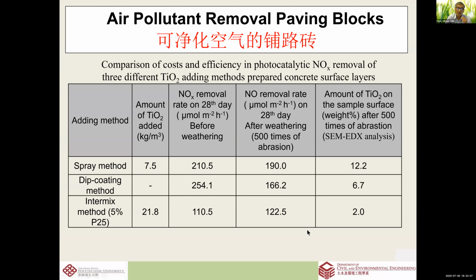So it's quite clean. We also developed different coating methods with TiO2: spray coating, dip coating, and intermix coating. We developed these methods with different efficiency, and the amount of TiO2 ranges from very little to very high, and the efficiency could be quite similar. So I think we are very happy with this particular method. I think we published this paper as well. If you are interested, you can search for it.